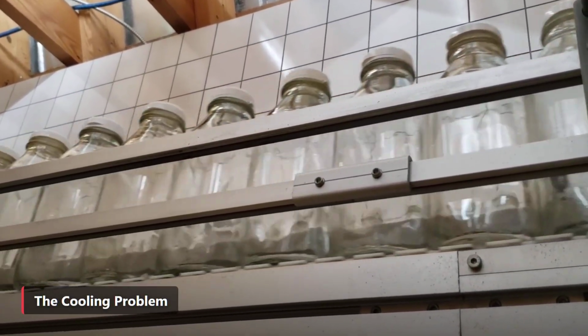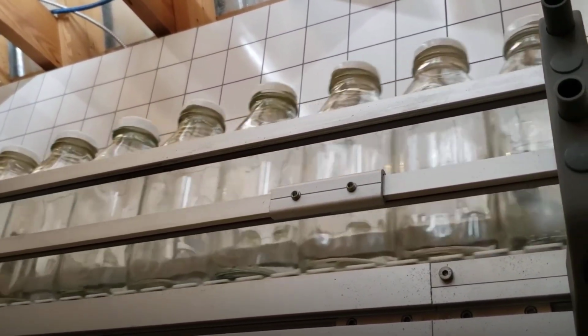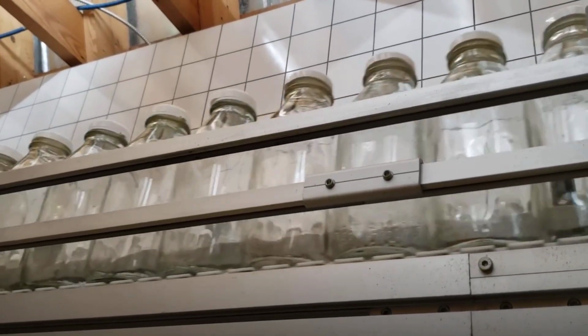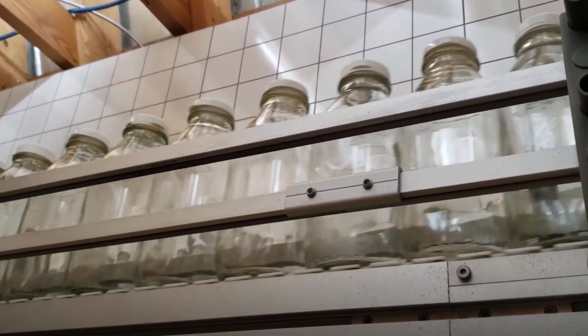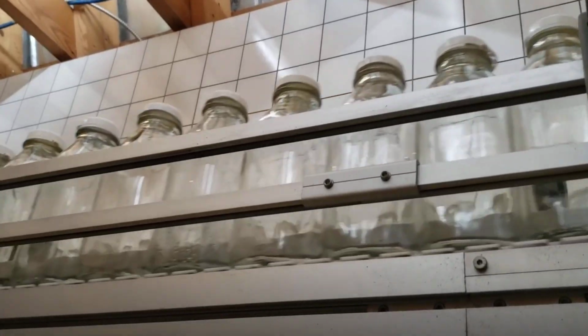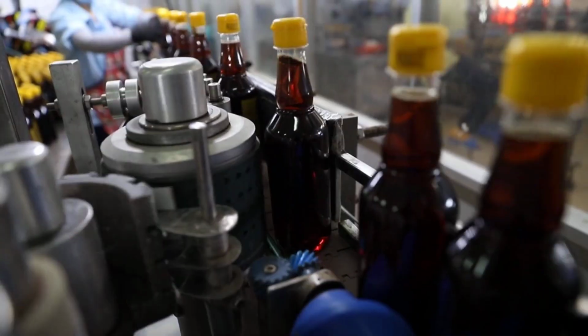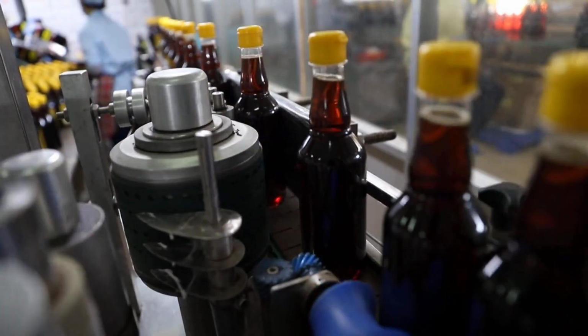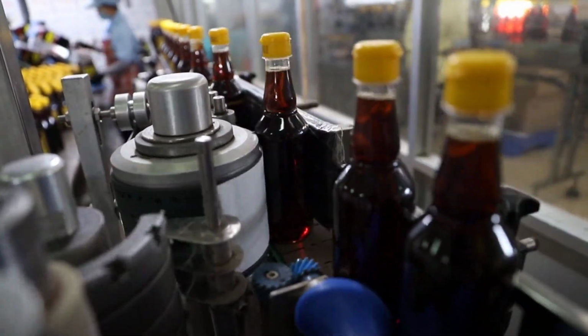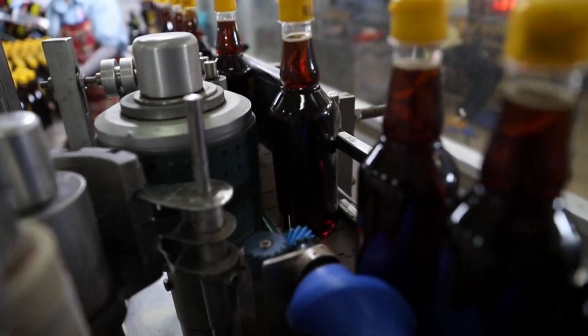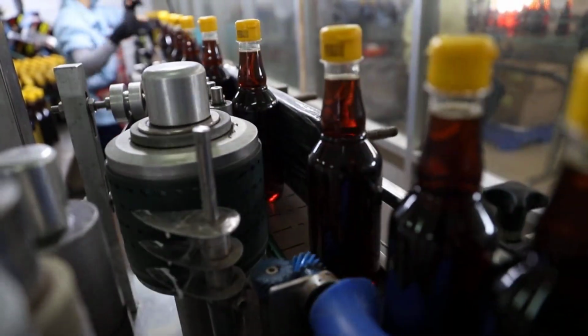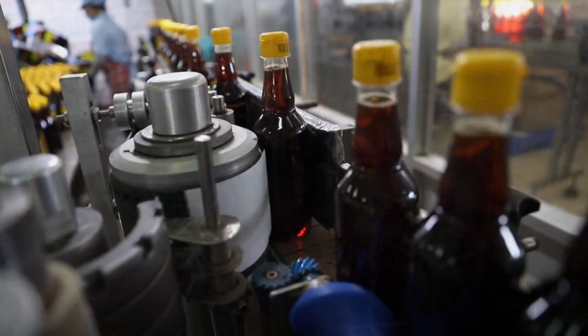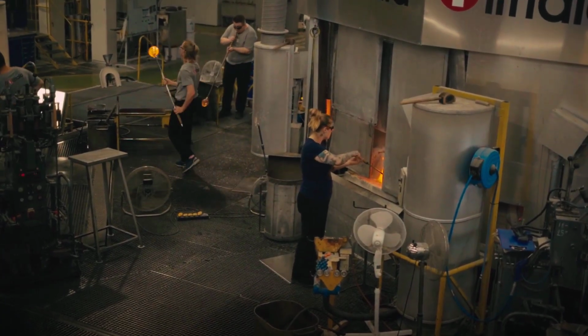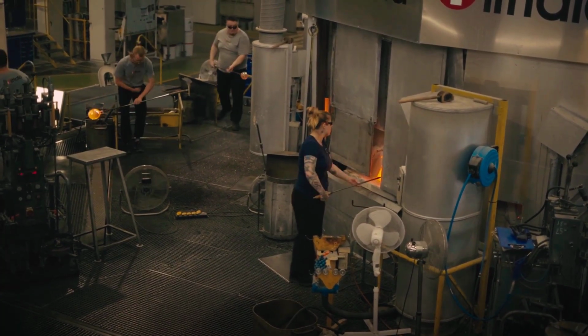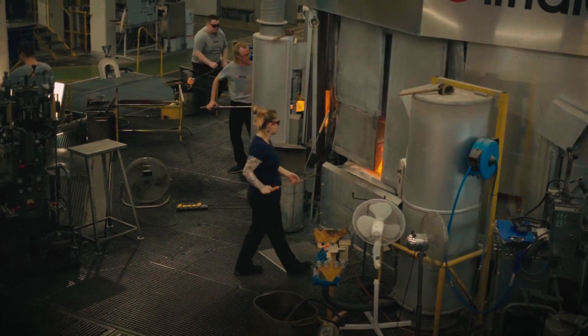Here's something most people never realize. Cooling glass is far more dangerous than heating it. When hot glass cools unevenly, the surface hardening while the inside is still hot, it builds up enormous internal stresses. Left unchecked, those stresses can cause the glass to crack or even shatter on its own, sometimes hours or days later. To prevent this, freshly formed glass is passed through a long, temperature-controlled oven called an annealing lehr.